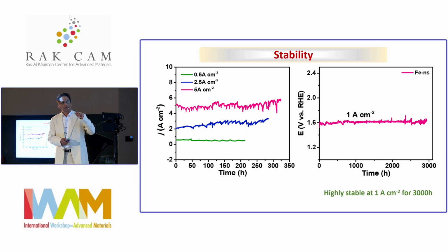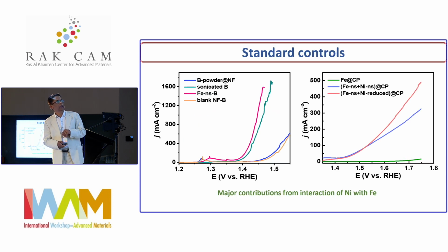So you need nickel foam and you add the iron nanostructure. With the reaction, it forms an active interface, like a spinel type of interface, and gives this high activity.